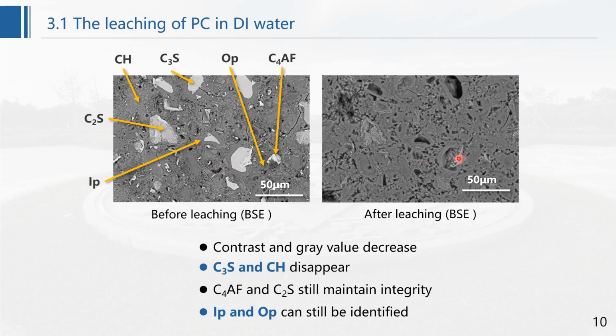C3S and CH all disappear from the matrix, leaving holes in the matrix. C4AF and C2S still maintain integrity. Here is the C2S, here is the C4AF. They still maintain integrity. Inner product and outer product can still be identified in the matrix.